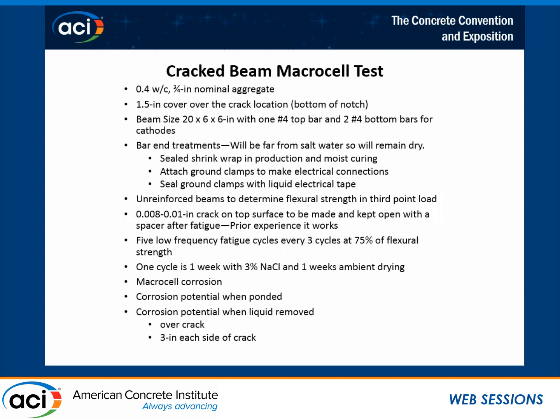So we had the bars a little bit more than 1.5 inches down, and we had a notch that brought it down to 1.5 inches over the crack. And the beams were large. These were normal 6x6 flexural beams. Bar and end treatments: we protected the ends of the bar so there would be no corrosion over there, and the dam was far away from the end treatments, so that we're not getting any crevice corrosion occurring at the ends of the bars that could mess things up. But that's for more on the corrosion end.